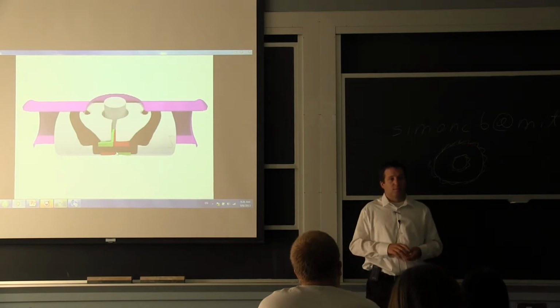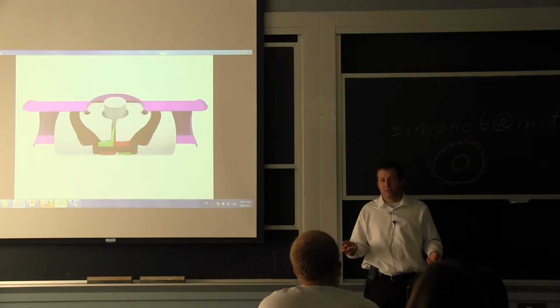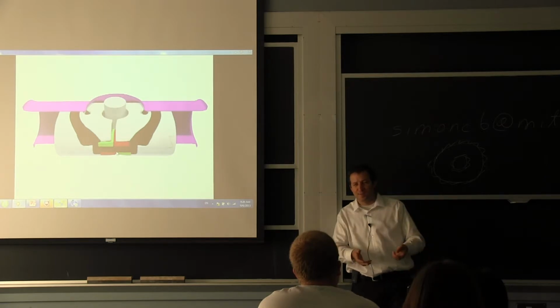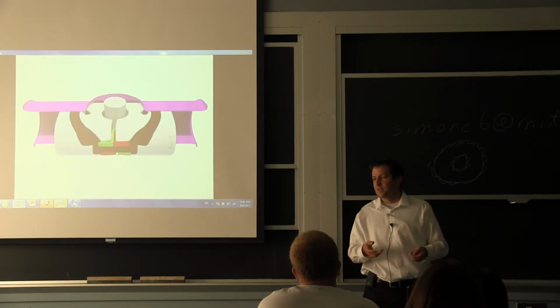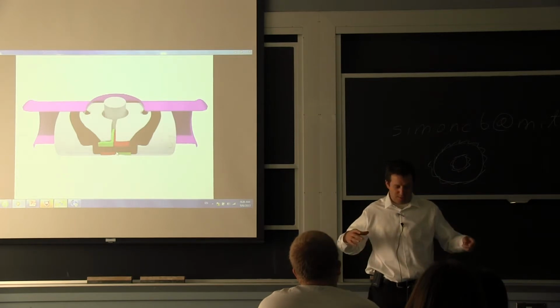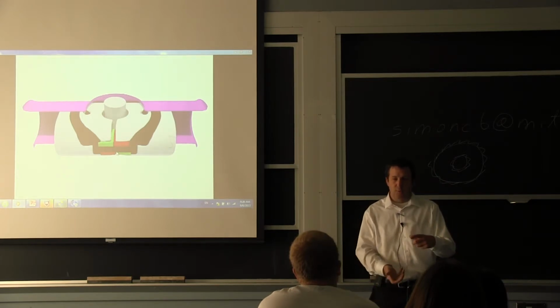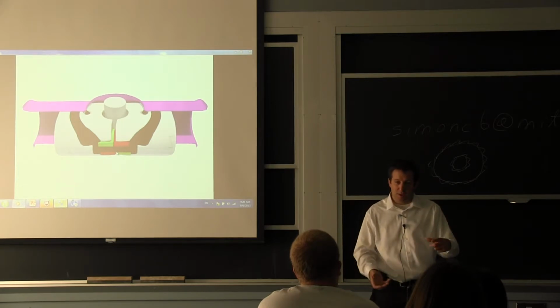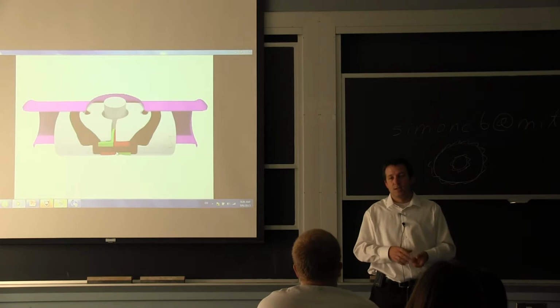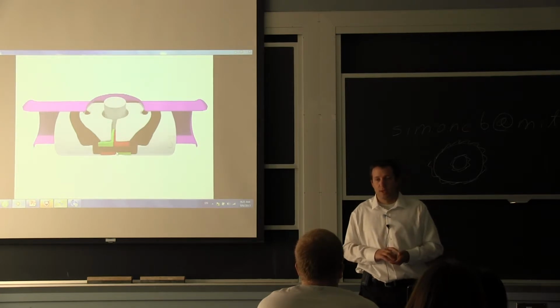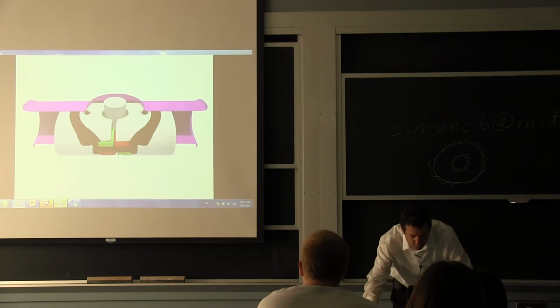So you have a lot of things to take into account if you're going to make a change. And what we've seen in the past is people making changes, just saying, well, it looks the same, or it doesn't look the same, or it's good enough. We tested it. But if you test it just by closing it and then you put the pressure, it's very different than when you have some flow and then you try to activate it. The speed and the quality of the match is a lot more important in a dynamic situation. So that was the example of going after the fact and finding out what didn't happen correctly.